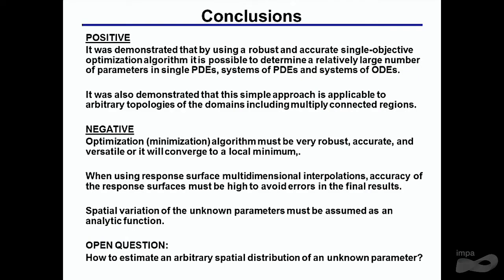And of course, in summary, the positive thing about this approach of using hybrid optimization is that it works on a number of different applications for single and systems of PDEs and ODEs. It can work in 2D, 3D domains, multiple domains, fine. The negative thing is that optimization, minimization algorithms must be very robust, very accurate and versatile, or they will converge prematurely to a local minimum. And when using response surfaces to speed up the whole thing, with multidimensional interpolations, the accuracy of the response surface must be high to avoid errors in the final results.